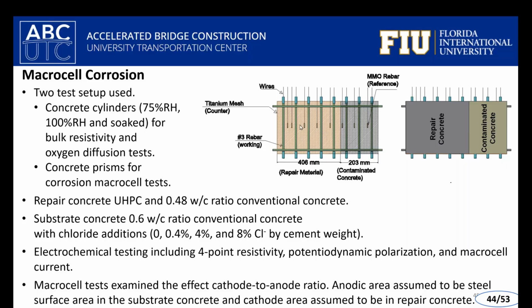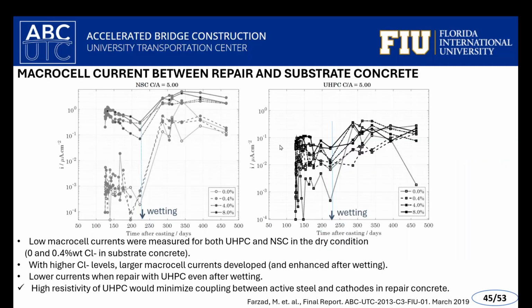So here's a schematic of the test prism. Some of the bars are in the contaminated substrate concrete, and some are in repaired UHPC or normal strength repair materials. So I'll try to go a little more quickly. This graph shows the current that develops when we have normal strength concrete repair material compared to the UHPC repair material. Both graphs represent the rate at which corrosion can occur.